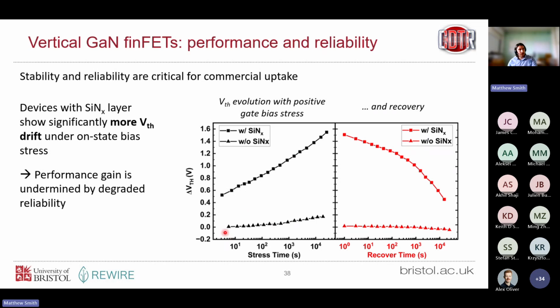So here we've got the first generation devices, without the silicon nitride, and then the second generation devices, these high breakdown voltage devices that have the silicon nitride. We can see that with stress time, our threshold voltage for those first generation devices is quite stable. For those second generation devices, it's all over the place. We get this quite steep increase here. Now, somewhat good news is that it recovers. If we take that bias away and then look at the recovery time, it does drop back down. It eventually does reach 0.